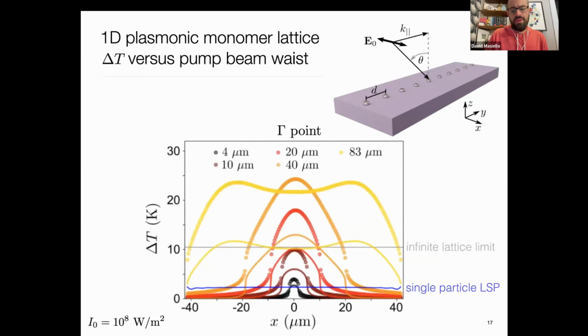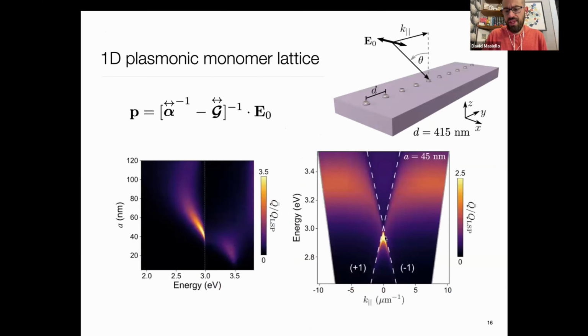And so the first thing we did is we just simply illuminated the lattice. This is at the gamma point under normal incidence with a plane wave field where we just blew out the width of the plane wave. We took a finite lattice of 80 microns in overall length, just a 1D lattice, and blew out the width from 4 microns centered at the origin of the lattice all the way out to a big broad beam waist that covers the whole thing. And the frequency that we chose to excite the system was at the surface lattice resonance frequency that you see here. And I'm contrasting that back to the single particle frequency, down here.